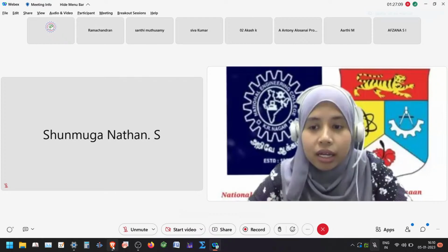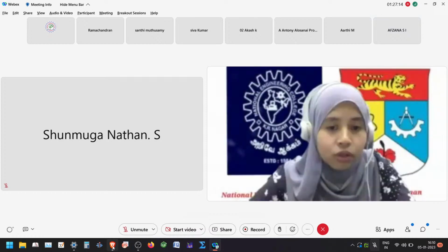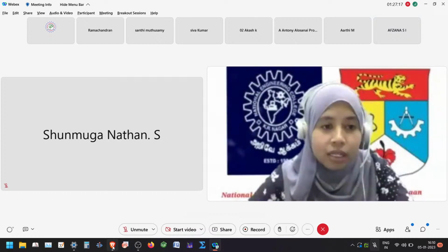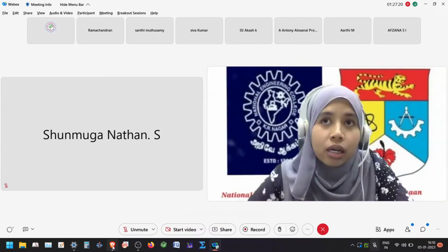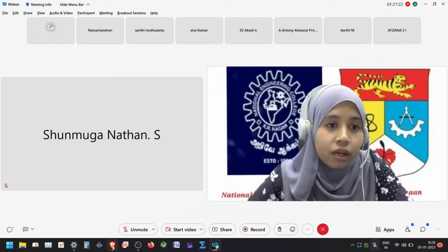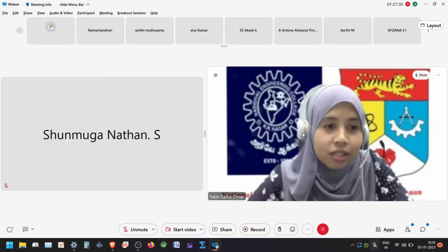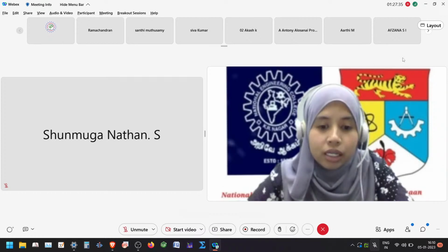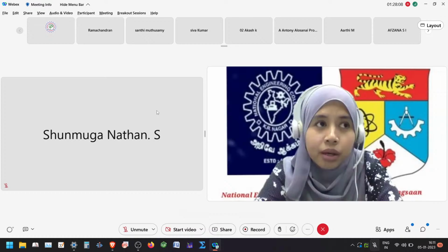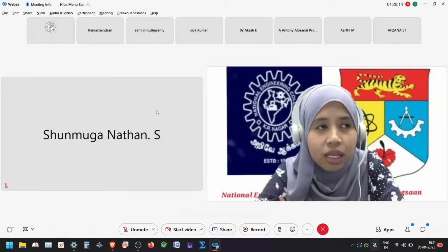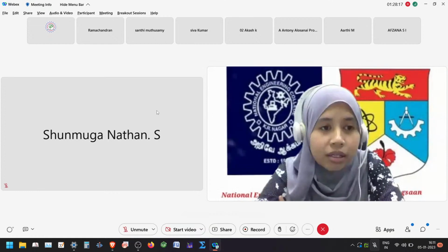The operating voltage of supercapacitors also depends on how you prepare the material and how you assemble the device. But commercialized supercapacitors get a 3 volt potential window. So it depends on the materials. If you want a single device with a very high potential window, what you can do is either enlarge the electrode, or you can connect more than one device. To conduct the experiment using 1 ampere, but some potentiostats are not able to conduct experiments at high current.